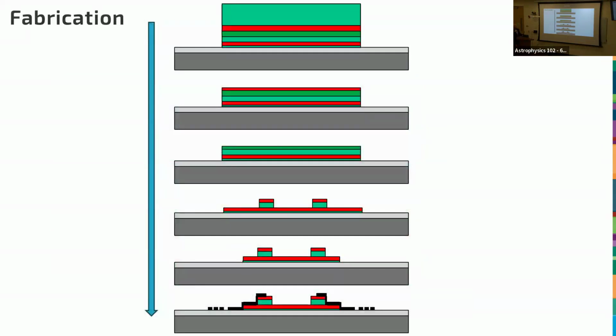Then we're going to use these orthogonal chemistries to start removing the substrate. Then we have an etch stop. Then we remove that etch stop, and we stop on the next stop. Then we start doing something a little more sophisticated. There's a couple of layers here that have a graded carrier concentration, and their whole job is to get what's eventually going to be metal contacts up here to flow electrons in and out, down in steps to the very high resistivity of this amplifier layer.